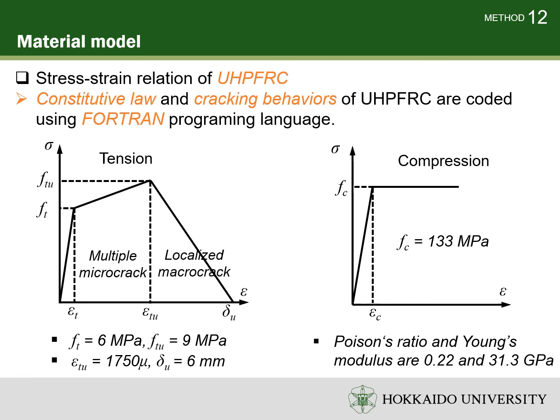Under compressive loading, the stress-strain law of UHPFRC is exhibited by a bilinear relation with a compressive strength of 133 MPa. The Poisson ratio and elastic modulus of 0.22 and 31.3 GPa are used for UHPFRC in this study.